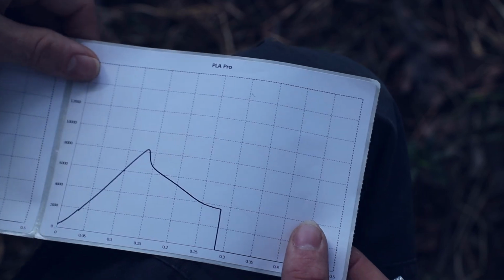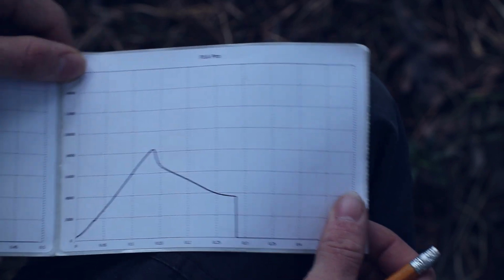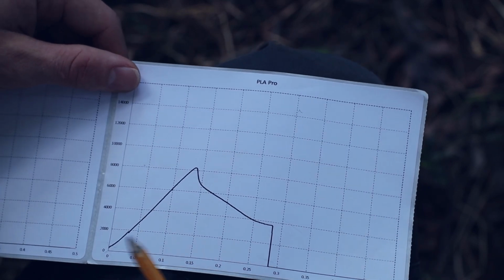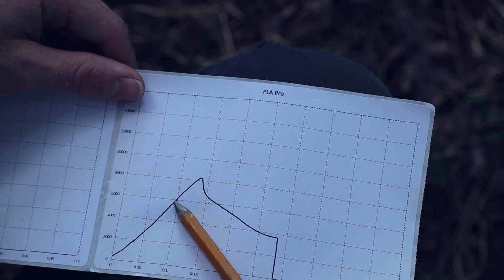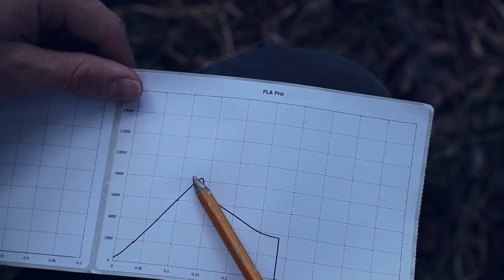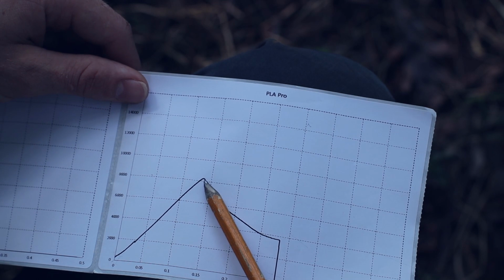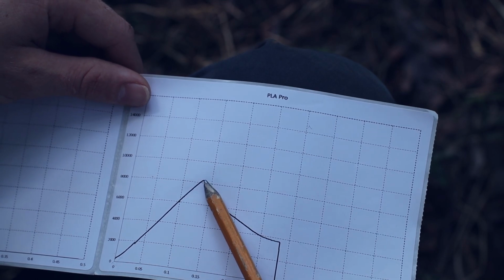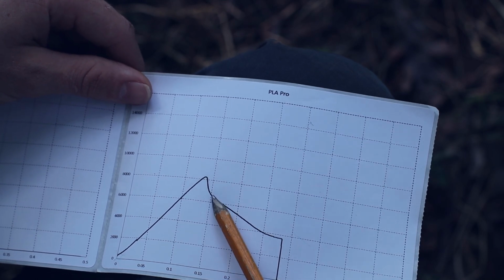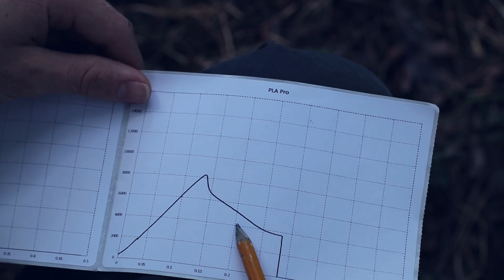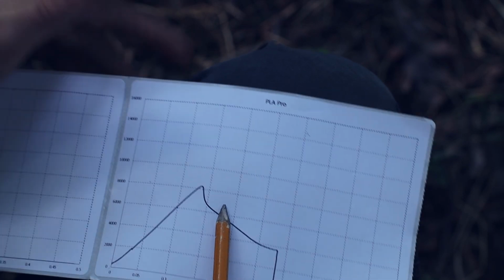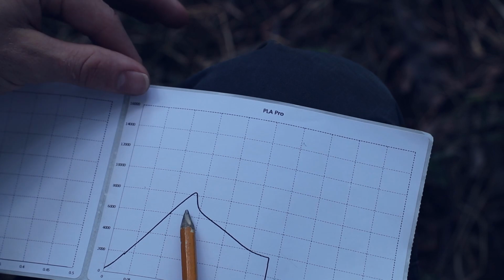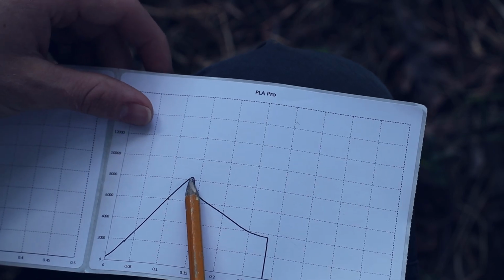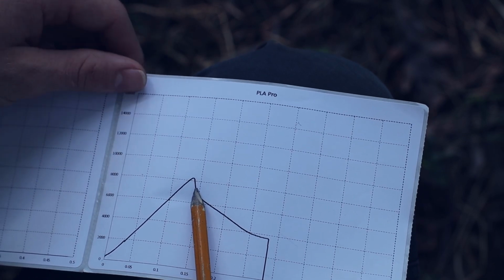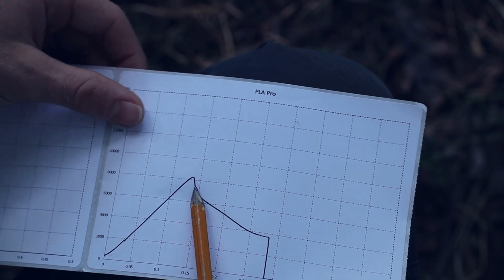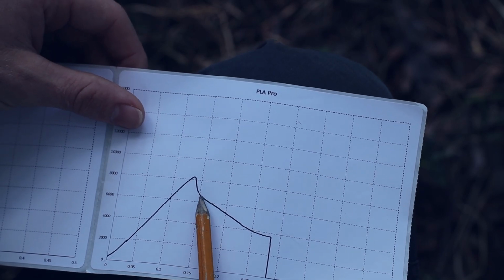And then we move over to the Polymaker PLA Pro, and this is kind of an optimal material as far as the stress strain curve goes. It's pretty nice, an extremely linear elastic deformation zone. And then at the end of that, it begins to neck, plastic deformation, a nice crisp transition point right there. We get plastic deformation, we get necking. And the necking is a rather complex phenomenon in different materials, but in this case, it's caused when the material begins to plastically deform, there's a lot of friction and heat created, and that heat softens the PLA Pro enough where it begins to neck.